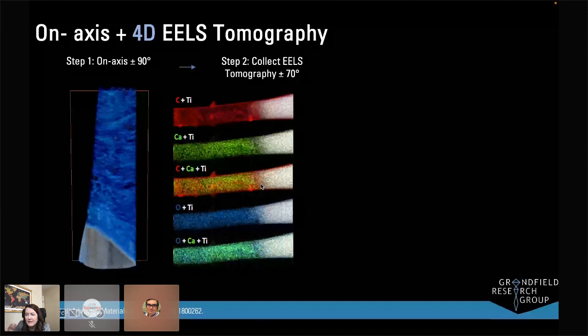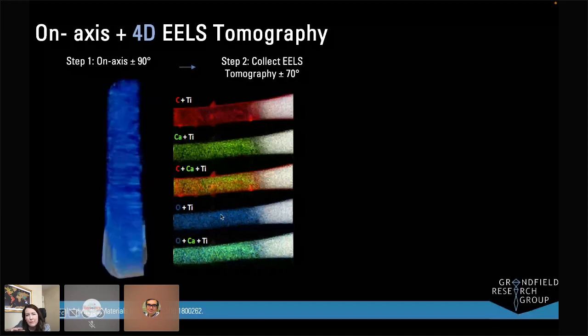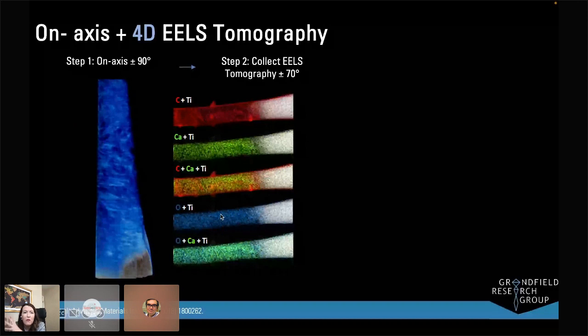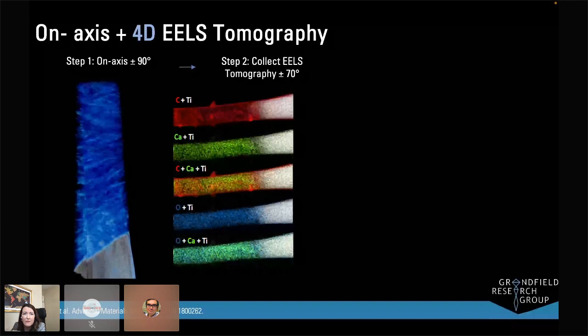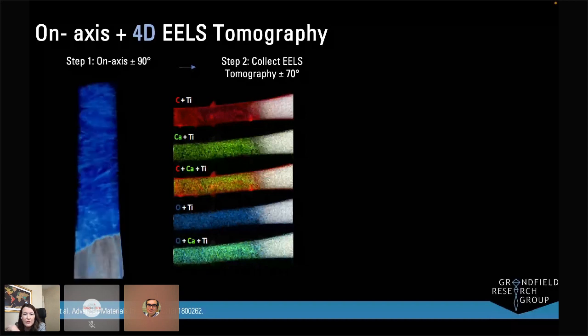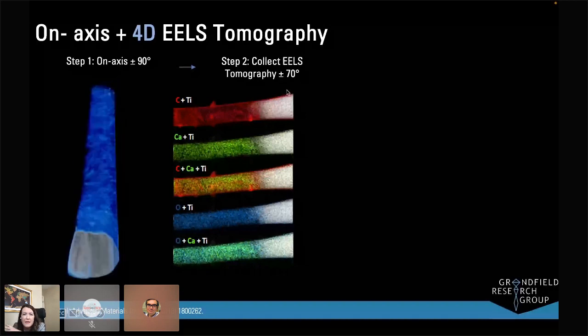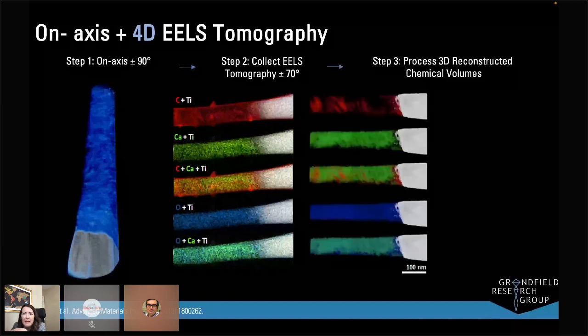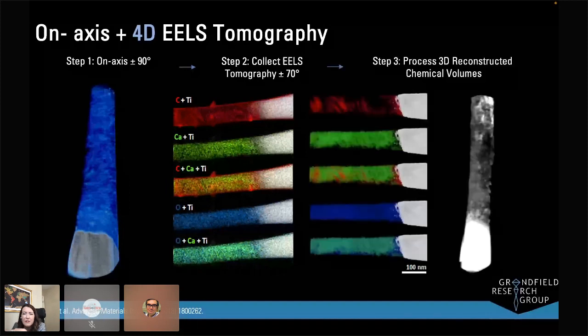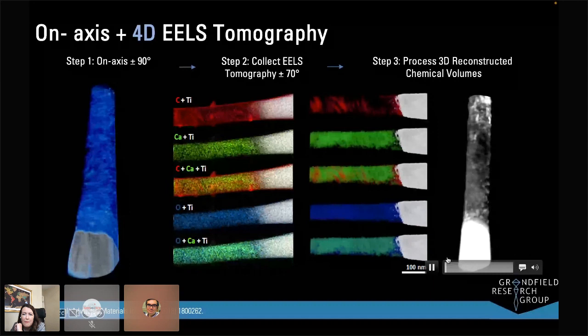At each angle, instead of just taking an image, we take a spectrum map and can plot out in 2D where all of the elements are contained. We repeat this over all of the angles we're able to tilt to, and we can record and reconstruct these elemental maps into a 3D volume. So now we have a volume that isn't just the images put together, but all of the elemental signals on top of one another.